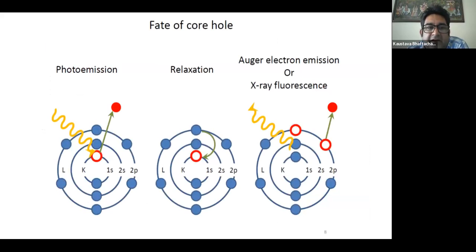So what really happens? If we put an X-ray on the element, the core electron gets ejected. Now, once one core electron gets ejected, the kinetic energy of this electron is measured by the detector. That gives me the model for XPS, that is X-ray photoelectron spectroscopy.